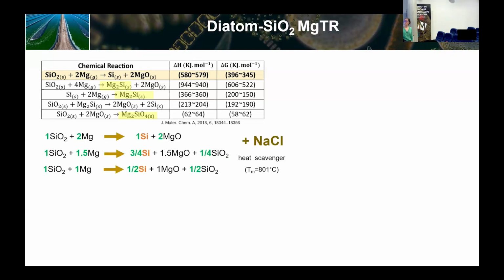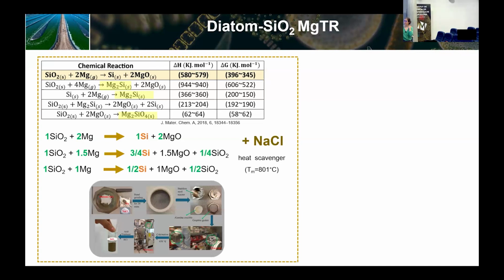So what we try to do is play a bit with the stoichiometry of the reaction to go to a situation in which we will have silicon-rich SiOx, and then more of a silica-rich SiOx, to see what happens. So we just mix all the components together. We add sodium chloride because we want to go to a larger scale for this. If the reaction is so exothermic, we will need an agent to buffer the temperature changes. Sodium chloride is great because the melting point is 800 degrees, so if there is an excess of heat, the sodium chloride will melt and everything should be okay. So we use a lot of sodium chloride, and then we did some reductions at different scales, from milligrams to 2 grams. We are trying to go to 100 grams, but then all of this is a mess.